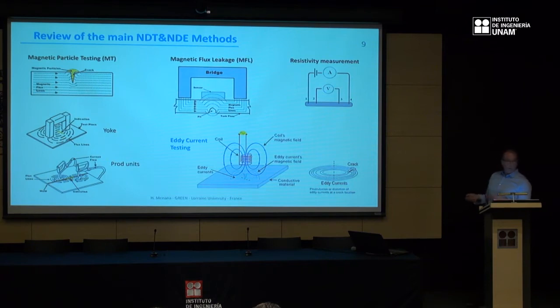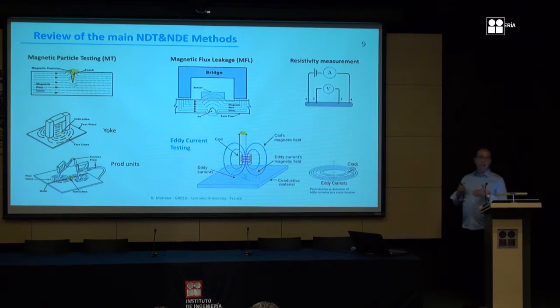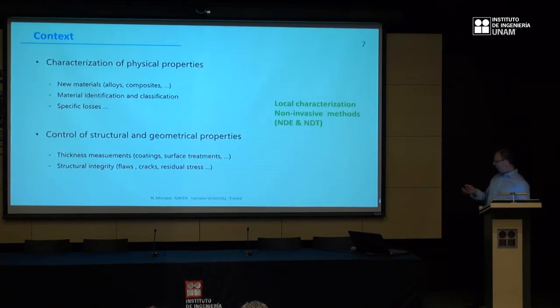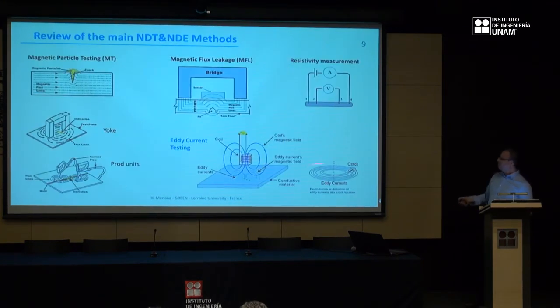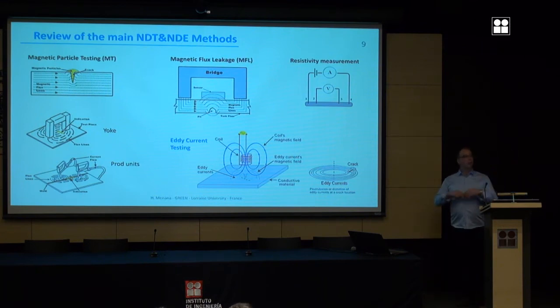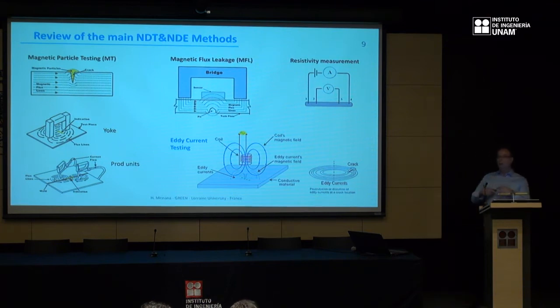The presence of a flaw in the material will deviate the current in the material, since the current cannot go through the flaw. This deviation will result in a change of the distribution of the magnetic field in the environment of the coil. That will introduce another change in the impedance. So we make a correlation between the impedance change of the coil and the geometry and the physical properties of the tested material. This is the basic principle.